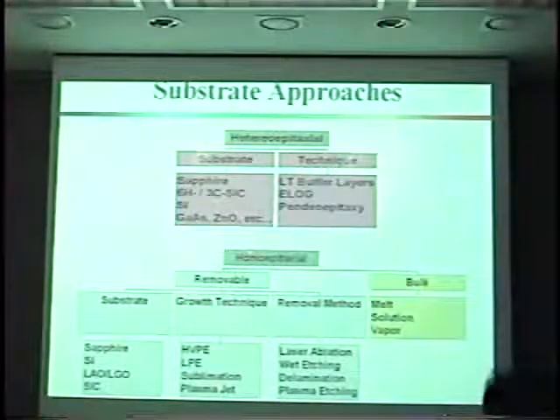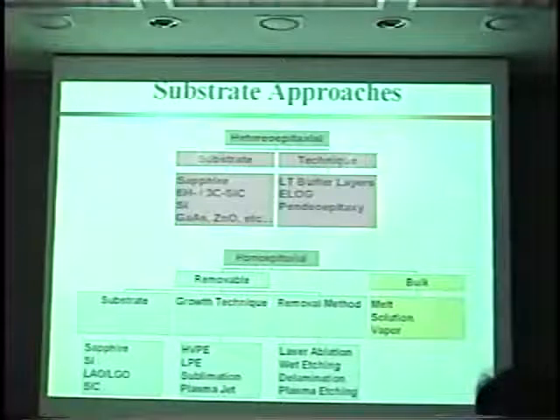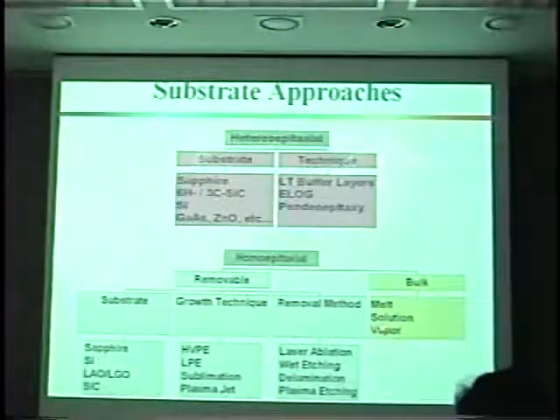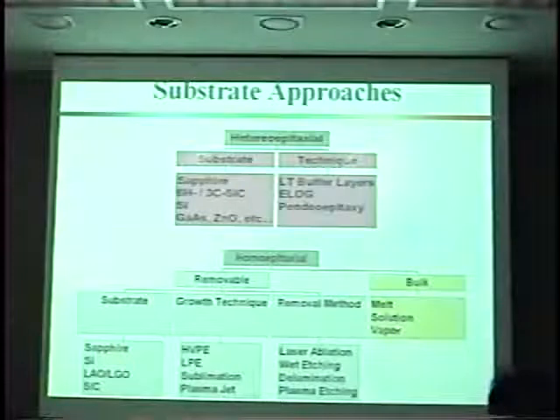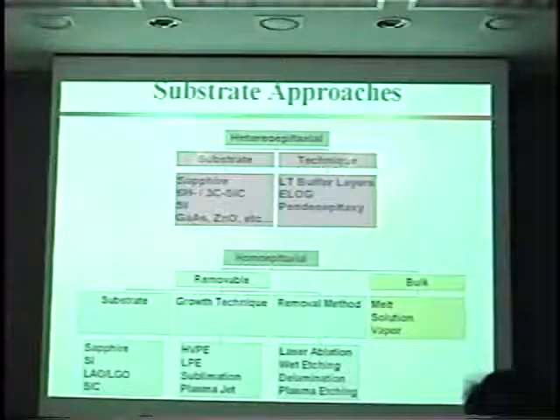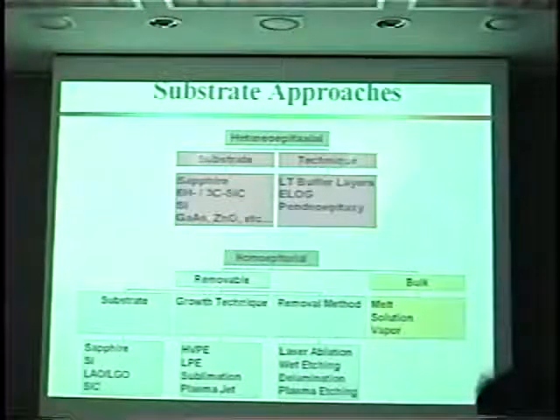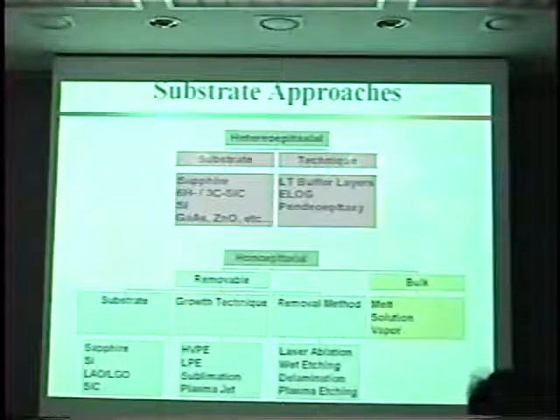The other approach, of course, which is what's done often, is to do homoepitaxial, that is to find a gallium nitride substrate. And there are two ways that people have approached it. One is to do bulk growth from the melt. The melt is at awful high temperature, so solutions are generally selected, finding an appropriate solvent and growing from the solvent, which has been attempted by several workers, and also to do sublimation, vapor transport to grow from the vapor phase. The other approach is to grow heteroepitaxy, grow a very thick film at a fast rate, and remove the substrate to leave behind a freestanding wafer of gallium nitride. So those are the two approaches.